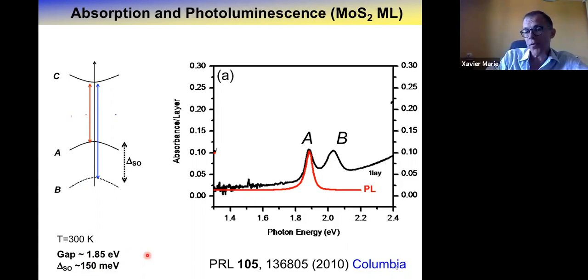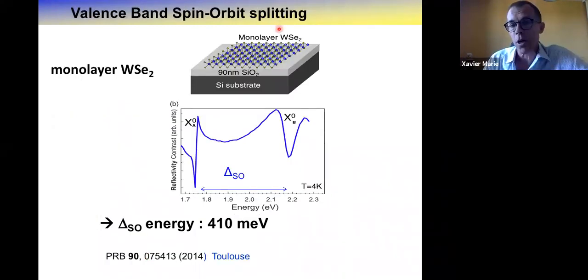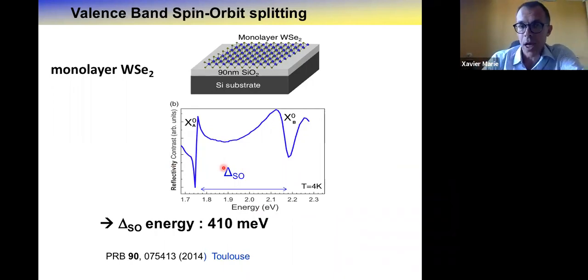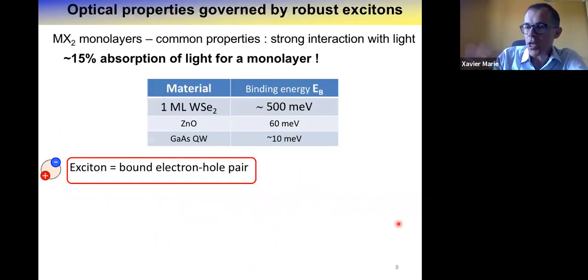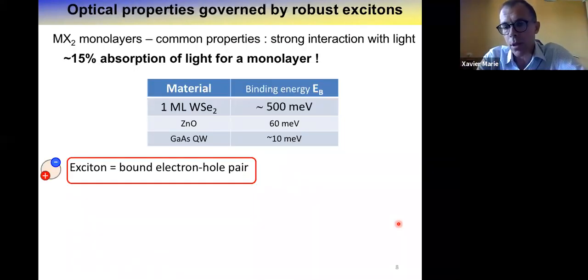This is for MoS2. If you do the same on WSe2, here a typical sample we all investigate, I will call this the first generation of sample, basically exfoliated monolayer on the SiO2 silicon substrate. Here, it's not absorption or transmission, it's a reflectivity contrast, differential reflectivity as a function of the energy. And you clearly see again two very strong resonances associated to the two transitions involving the two valence bands I presented. Here, tungsten WSe2 monolayer, heavier atom, stronger spin orbit splitting, no surprise, the splitting is almost three times larger in WSe2 compared to MoS2. So this is very basic characterization where you can start to have information on the band structure.